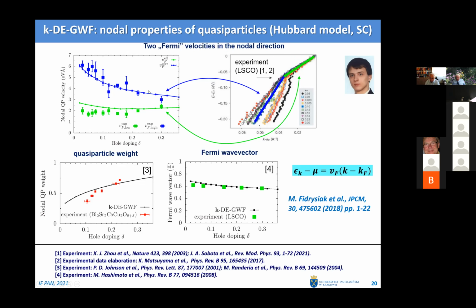That's this velocity, which I already showed within the static approach. Here is the alternative approach in K-space. And again, you can see here, since this is a later paper, the fitting is even better for lanthanum strontium. But then they observe a very interesting, very strange thing. We have a kink, a break in the dispersion, as if a new Fermi velocity was appearing, because if the dispersion relation is linear, the coefficient of proportionality between wave vector and energy is the Fermi velocity times the Planck constant h-bar.